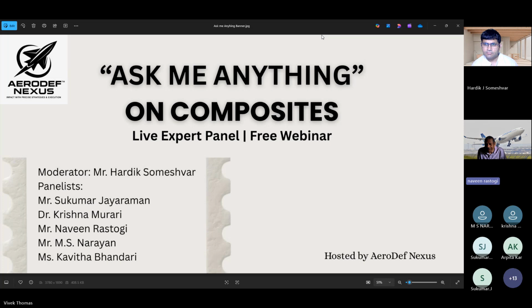Puck and Hashin criteria, which you're talking about, are used, but most of the time they are used for progressive failure analysis, not for quickly designing structures. Because when you're designing structures for damage tolerance or effects of defects and things like that, including environmental effects, you get your max stresses and strains in the ply, and you end up applying a max strain or max stress criterion, which gives you an answer pretty quickly.